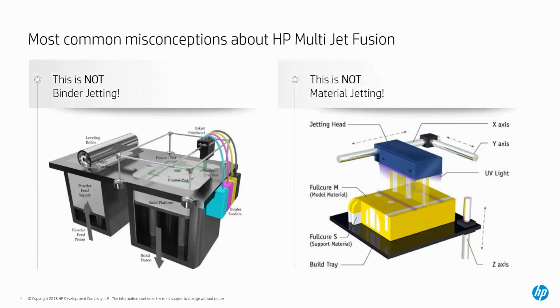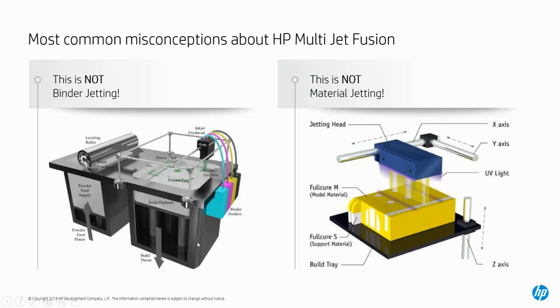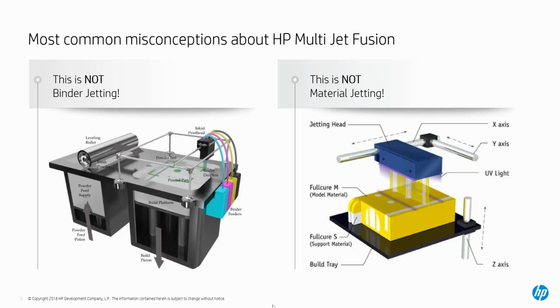One thing that we'd like to point out is that even though it is a print head based system, it is different than other technologies that use print heads in order to make final parts. On the left-hand side, one major confusion is people refer to it as binder jetting. HP Multi Jet Fusion is not binder jetting because we're using a thermoplastic and the part is actually fused. So when the parts come out, you have a fully functional part without the need of infiltration of the parts afterwards. When you think of binder jetting, they are using 2D print heads, but they are using essentially CA glue in order to bind the parts together.